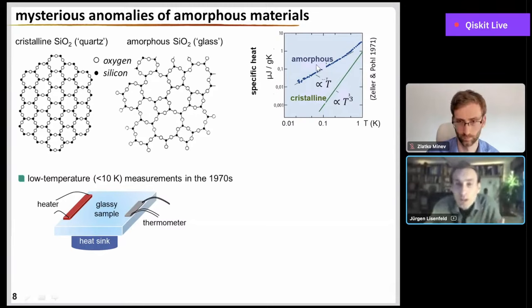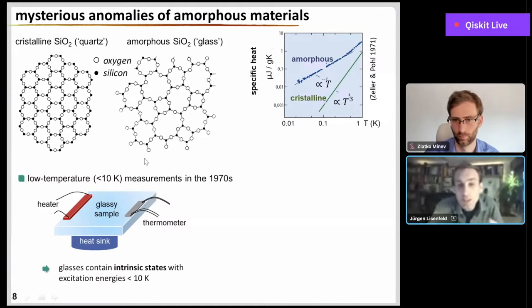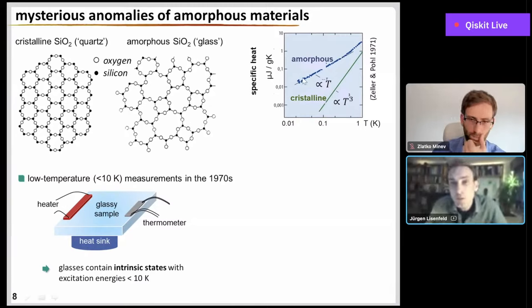And if you need more of this energy to heat up the amorphous material, this already tells you that there must be something inside this glass which absorbs these phonons so that they don't end up in the thermometer. So from this measurement, you can conclude that these glasses should contain intrinsic states which have these low excitation energies so that they contribute here to the specific heat at low temperatures.